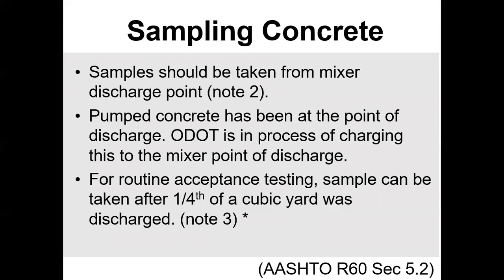For routine acceptance testing, samples can be taken after the first one-quarter cubic yard has been discharged. So for acceptance testing — just to figure out if the concrete looks good — after about a quarter of a yard comes out, you can test it and accept or reject the truck.